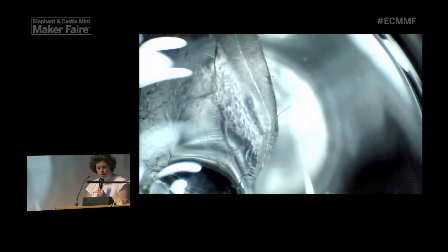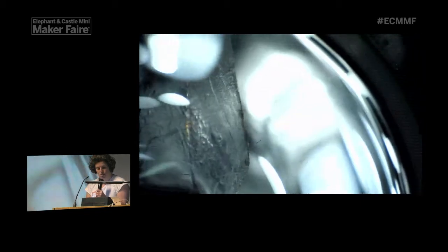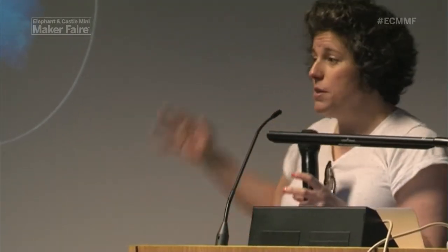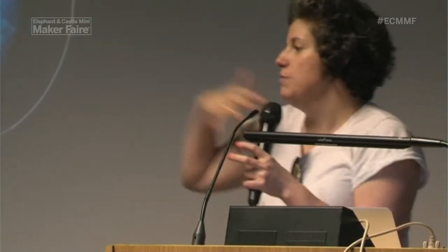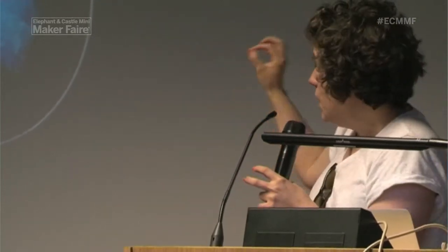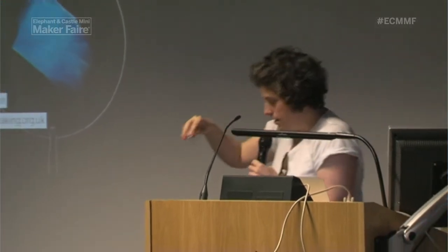But imagine it's like a foam. So you can sort of see it there. But in the right angle of light, it is blue. And the blueness is for the same reasons that the sky is blue. It's essentially about how light is scattered as it passes through the material. It's not a pigment. It's not blue like these chairs are blue because it's absorbing certain wavelengths and reflecting others. It's scattered by these microscopic pores. Imagine a meringue, teeny tiny pores, and that's what gives it this amazing lightness, but also relative strength. So that's some aerogel given to us by NASA.